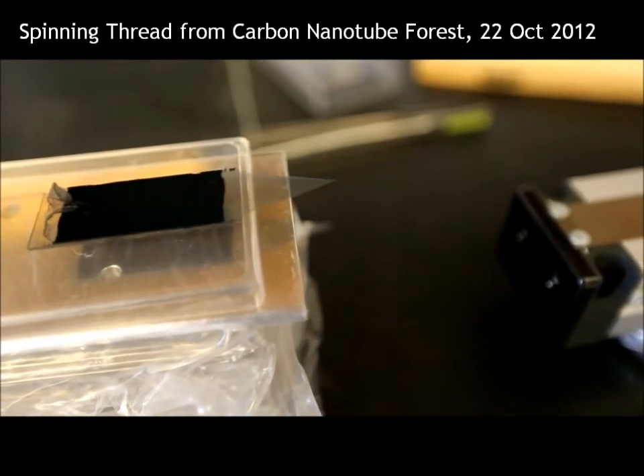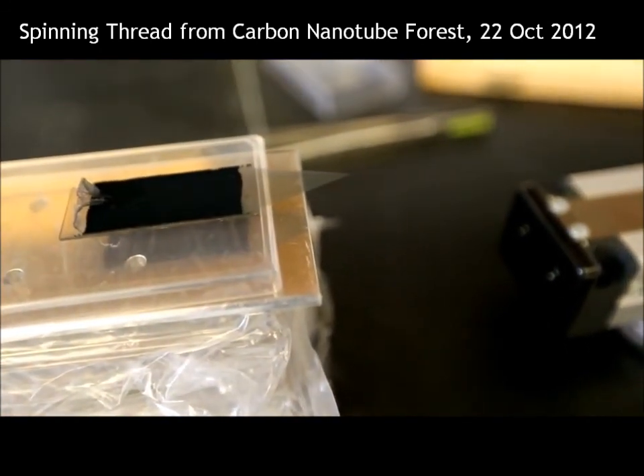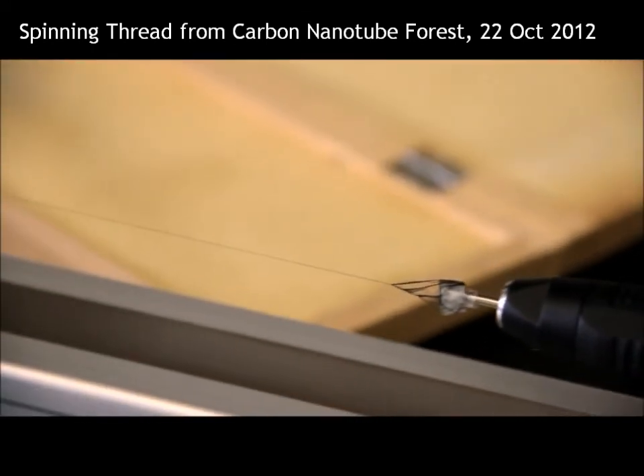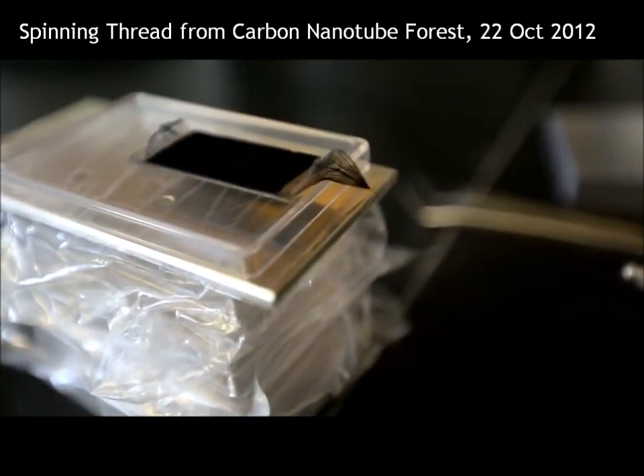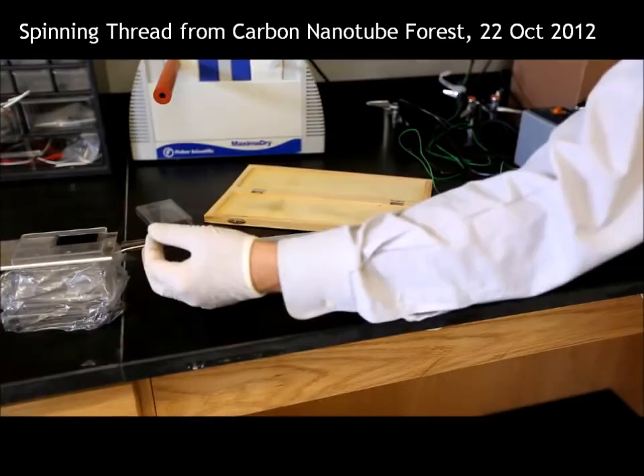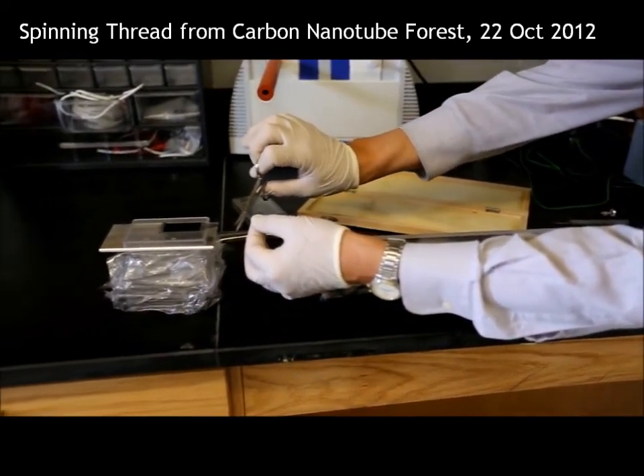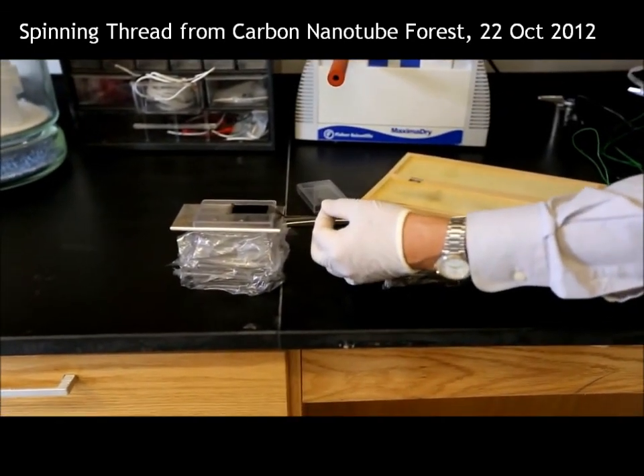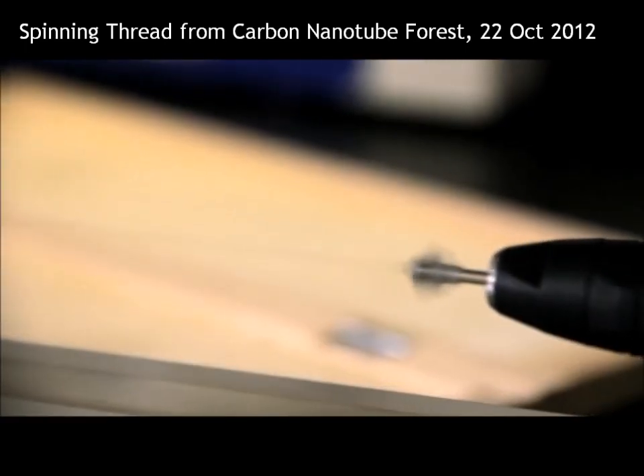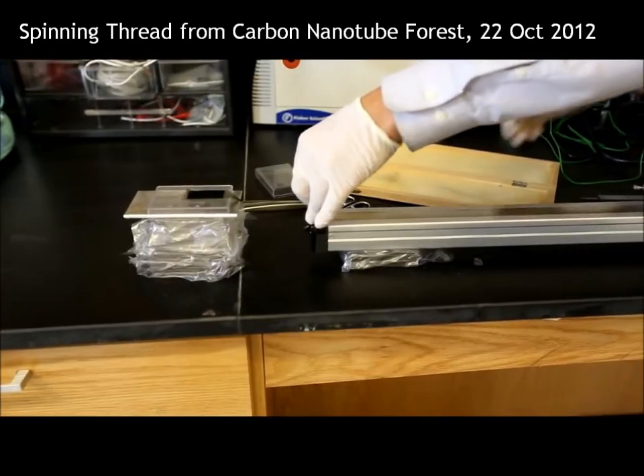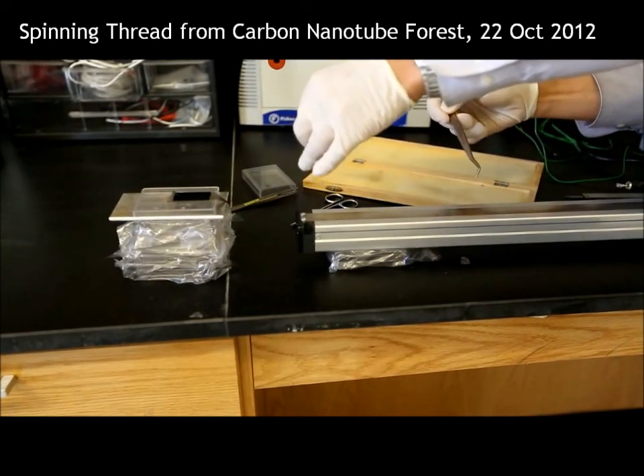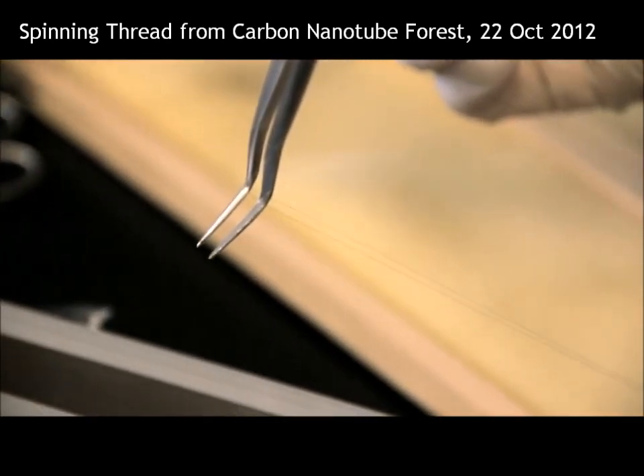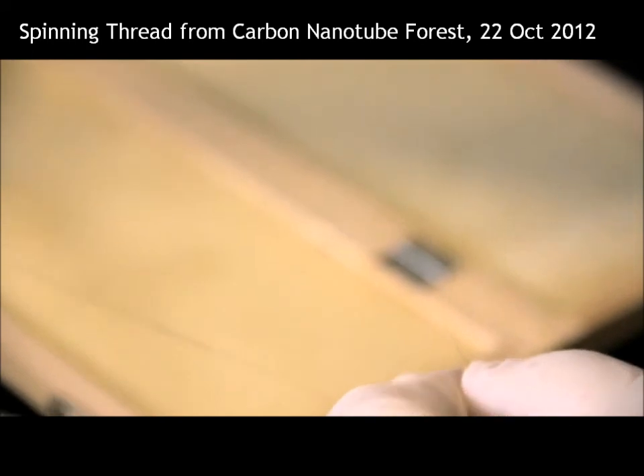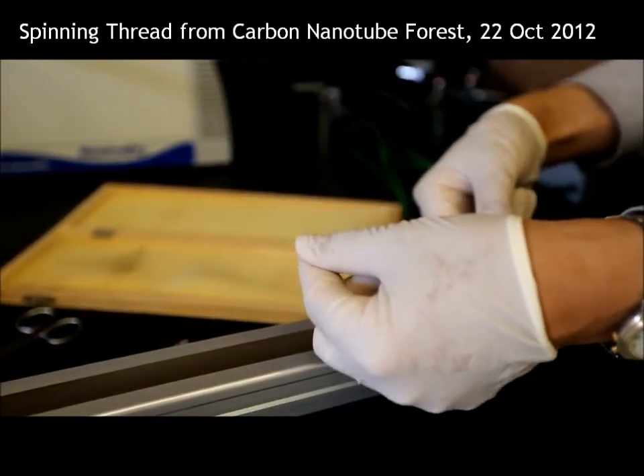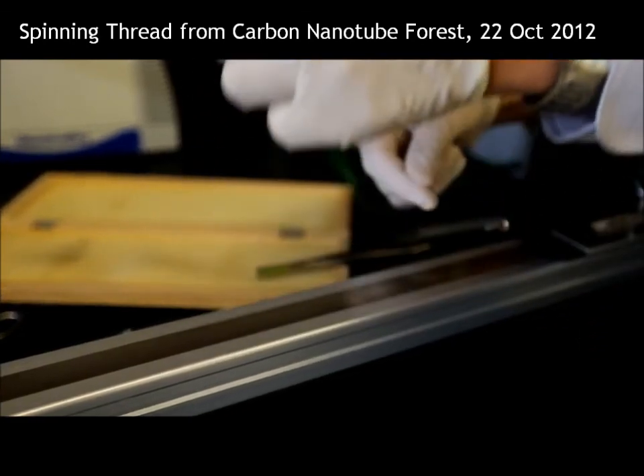What we'd like to do is make an ultra-strong, say stronger than steel, cable out of this material, which is as light as spider webs. This block of carbon nanotube forest can be spun into about 50 meters worth of carbon nanotube fiber. Right now, although we have a carbon nanotube thread, if we spun these threads together, twisting them, we could get a larger and larger fiber. To make it a little more stable, he has to keep winding it even tighter. Now he's broken the connection from the forest of carbon nanotubes. We're not spinning any new carbon nanotubes, but we're making the thread or fiber even tighter. Then you can see it's a little easier to work with more tension.